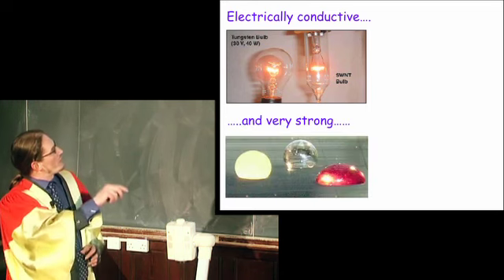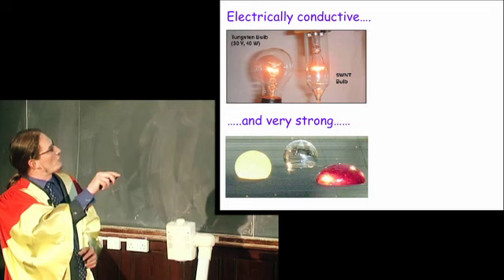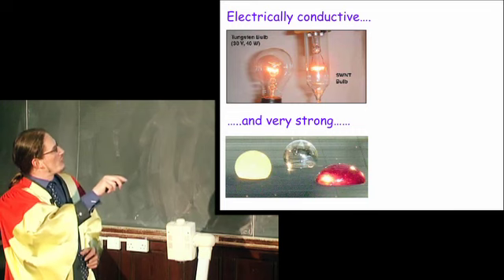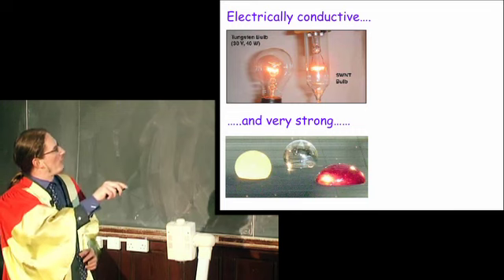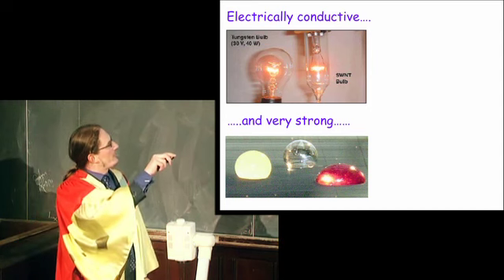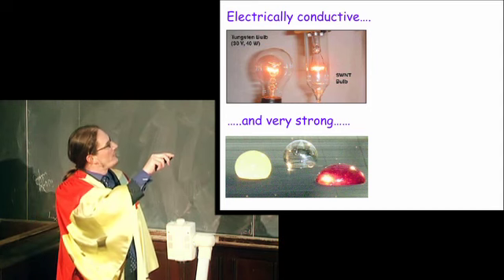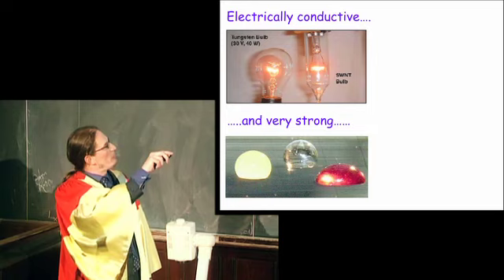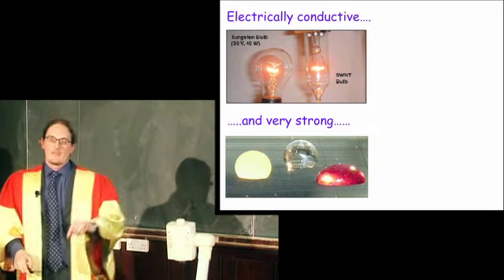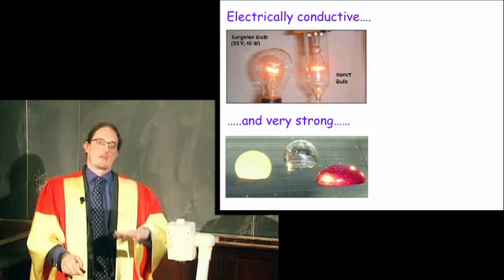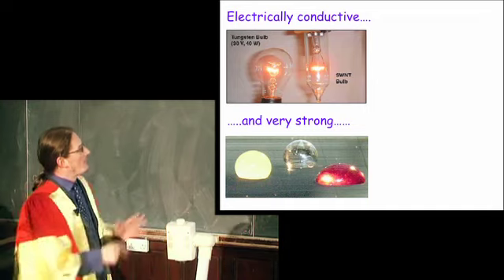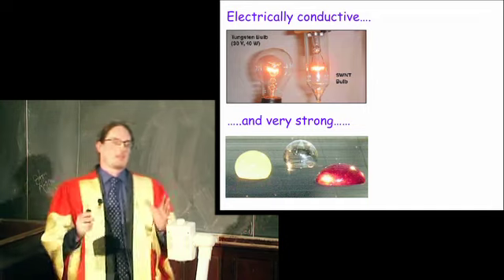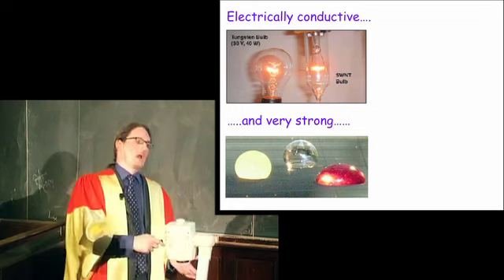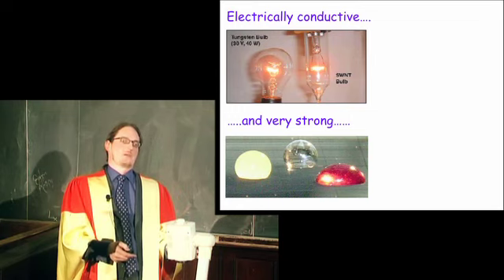And this is a picture of the sheet I showed you in the previous slide with droplets of water, grape juice, and cranberry juice on top. Now, the reason this is interesting is that the mass of the sheet of nanotubes supporting this droplet is 50,000 times lower than the mass in the droplet. And if that doesn't sound impressive, think about lying down and someone putting a weight 50,000 times your weight on top of you.